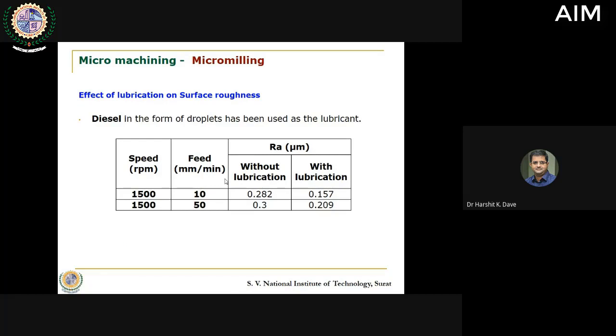One important finding was that if we are able to lubricate during the process, constantly supplying drops of lubrication, somehow kerosene did not work, somehow regular dielectric fluid did not work, somehow the oil that we usually use for lubrication did not work. And I don't know the reason still, but diesel worked well. So drops of diesel were put over there, because of which the finish that was obtained was in the range of sub-micron level. Without lubrication, you got the roughness value of almost 0.3 microns, and with lubrication it reduced